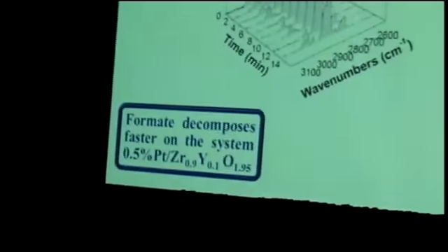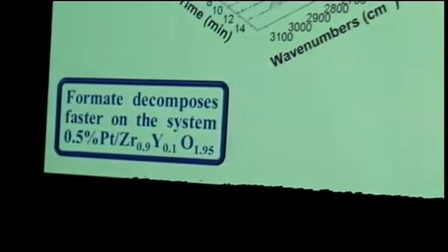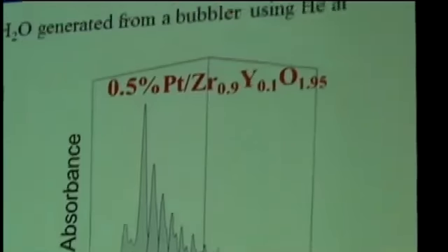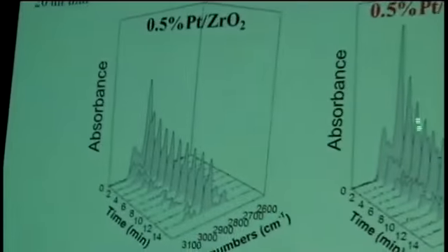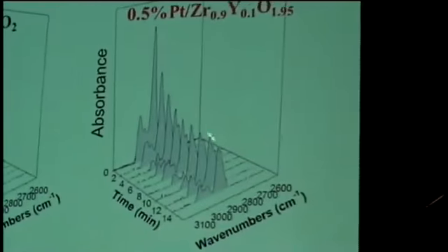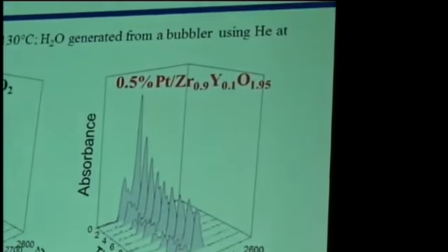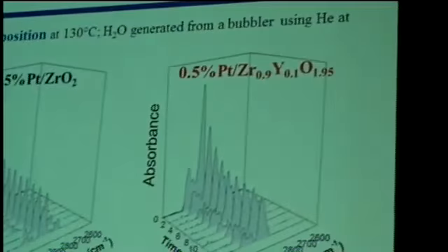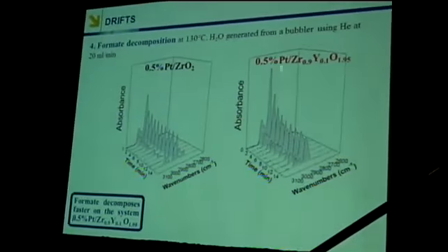Then we subjected the formate to steaming at very low temperature, here at 130 degrees, and you can see the formate is decomposing on both catalysts. But the decomposition rate is faster for the yttria-doped catalyst, and more significant as well.